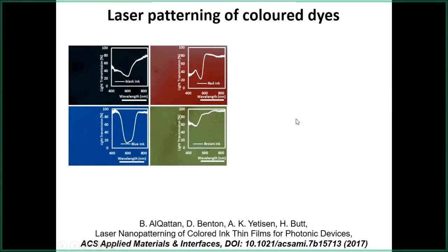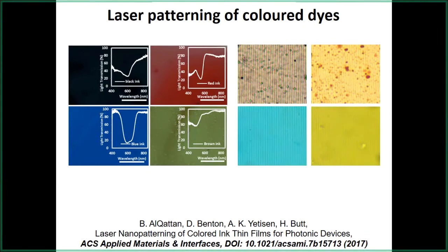Moving ahead, we wanted to try not only different shapes, but also different colors. This work of ours showed that as long as the laser is absorbed by the material that we are using, we can use a variety of materials. So we used different combinations of dyes with different transmission optical properties, and we were able to produce nanostructures out of them. This way of producing nanostructures, unlike photolithography or electron beam, where you are very specific in terms of the materials you have to use, is quite independent, quite flexible.